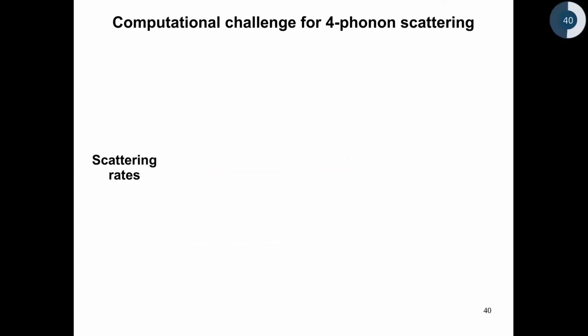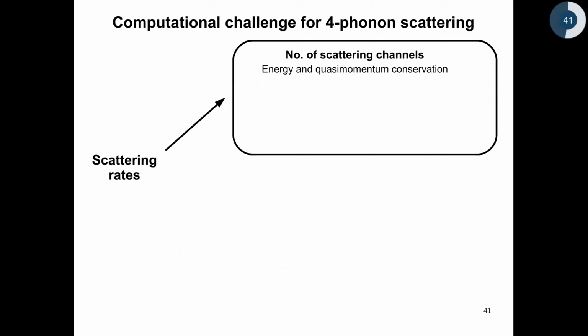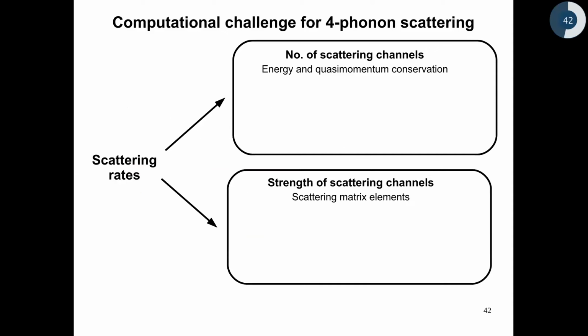So this process can typically be broken down into 2 sections. The first one is to count the number of scattering channels that are allowed according to the energy and quasi-momentum conservation constraints. And once we have this list of allowed scattering channels, we can calculate the strength of each and every channel. This is where the anharmonicity of the crystal comes in, which describes the strength of each and every channel. And putting these two together, we can calculate the scattering rates through Fermi's golden rule.